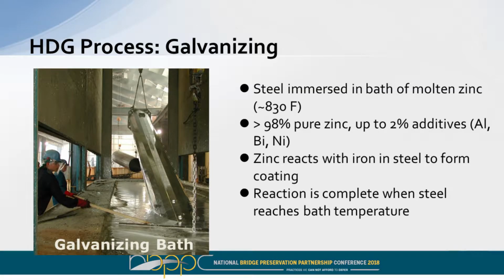So in the hot dip galvanizing process, the steel is immersed in a bath, gets up to 830 degrees. That's where the galvanizing process happens. It's 98% pure zinc in order to meet the ASTM 123 spec. It has about 2% additives of aluminum, a little bit of bismuth, a little bit of nickel. It reacts with the iron to form the coatings, which I'm going to show you in a second. And the reaction is complete when it reaches that 830 degrees.